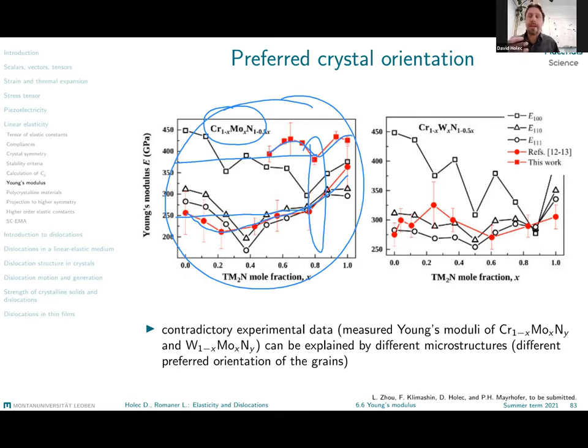You might say that there is a huge microstructural difference in your material, but maybe one of those materials is kind of polycrystalline, the other one is single crystalline, or that you have a lot of grain boundaries and fewer grain boundaries. It turns out that for those two particular measurements, the polycrystallinity, the amount of grain boundaries, was fairly similar. What, however, differed here is the preferred orientation of the grains.